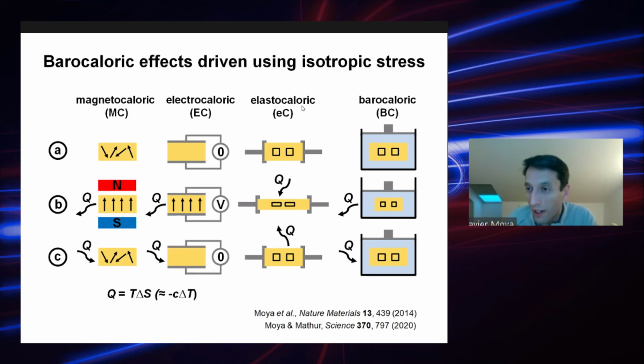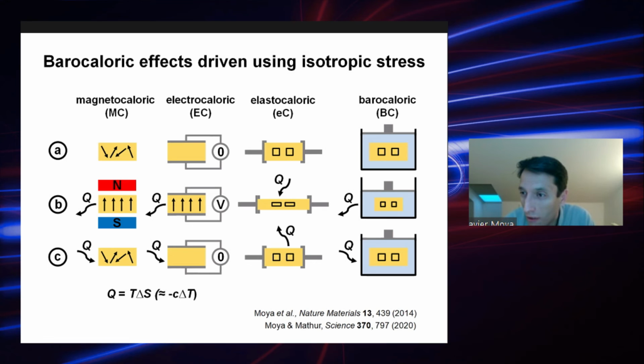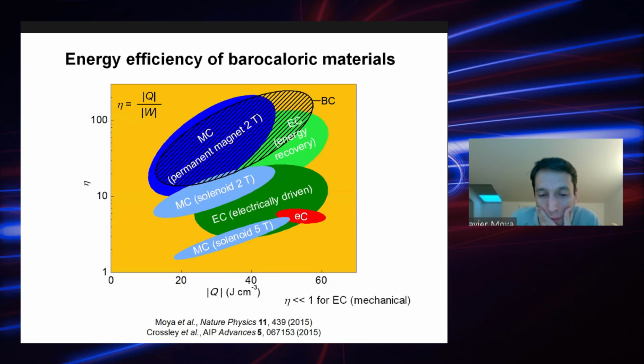And I will argue that barocalorics are really interesting, because in a way they overcome the problems that the other ones have. If you compare barocalorics with magnetocalorics, applying hydrostatic pressure is quite simple. You just need a fluid and a piston. Compared to electrocalorics, you don't really have breakdown in barocalorics, because even if the sample crumbles, it's going to still work. And compared to elastocalorics, you don't have so much fatigue, because the pressure is hydrostatic, so you can take the sample in a piston. So barocalorics are interesting for all these reasons, and we will tell you a bit more later in this talk. They are also potentially quite efficient. So if you calculate the energy efficiency of the material itself, this parameter eta has nothing to do with the device.